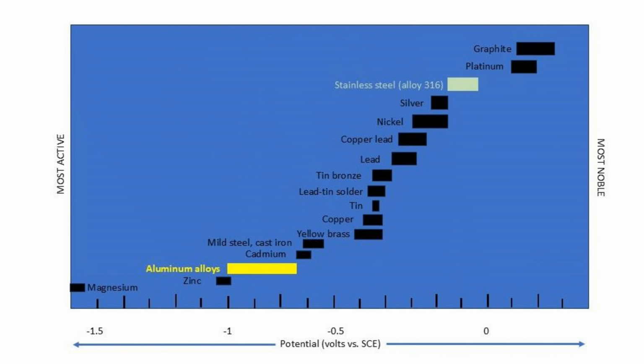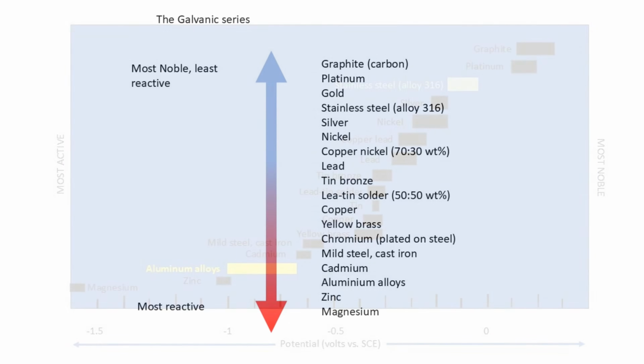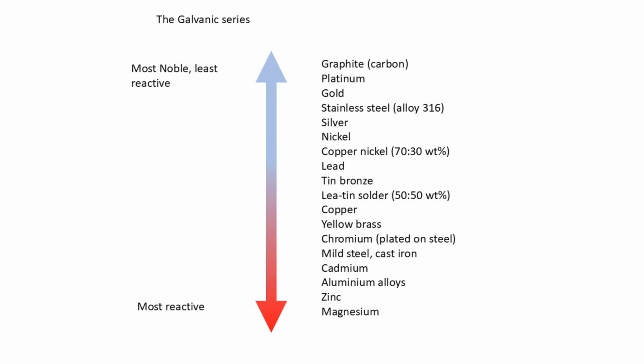So you can look at the galvanic series and see that cadmium is between aluminum and steel. If you put a cadmium spacer between the aluminum plate and the steel chassis, then you do not have metals with more than 0.2 volt potential difference, and galvanic corrosion will not occur, or at least it'll be very slow. The other thing you need to do is prevent moisture from connecting the two metals.